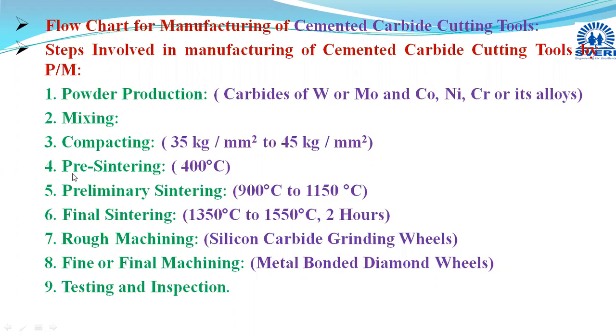The first sintering will be termed as pre-sintering, which is conducted at 400 degrees Celsius. Here, whichever lubricants we have added in the mixing stage are removed or eliminated by heating the component at this 400 degrees Celsius temperature. Then the preliminary sintering is conducted, heating the component at 900 degrees Celsius to 1150 degrees Celsius temperature zone.